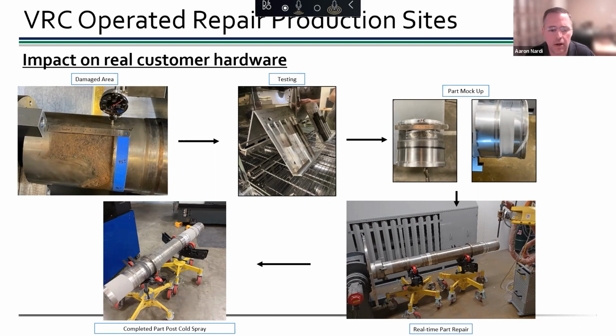So we filled the deep area, and then we did the fill on the full diameter. And so you can see by the time you're done, we have a sprayed part in 2 or 3 areas on the shaft. On these, we actually did some rough machining of the coating to get it close to dimension, and then we give it back to the customer because the dimensions were extremely tight tolerance, and they had equipment that was better suited to grind it to the finished dimension.